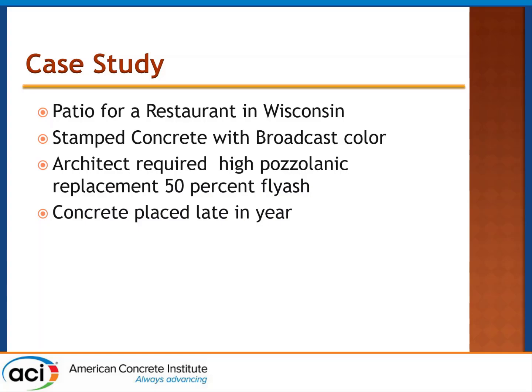But I'll give you a less structural but more relevant problem. There's a patio that was constructed, a restaurant in Wisconsin, stamped concrete with broadcast color. The architect required a pozzolanic replacement of more than 50% fly ash, and this did not make it down anywhere further than the lab or than the plant level, where the plant said, oh yeah, we'll just pull out 300 pounds of Portland cement and we'll substitute in 300 pounds of fly ash, which immediately gives us a yield problem,